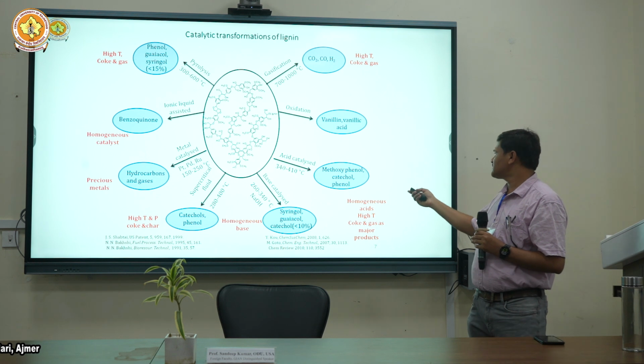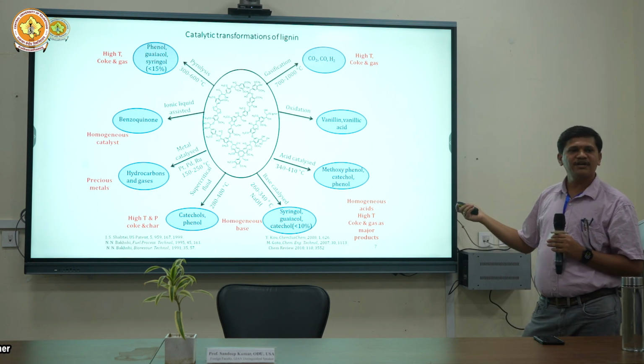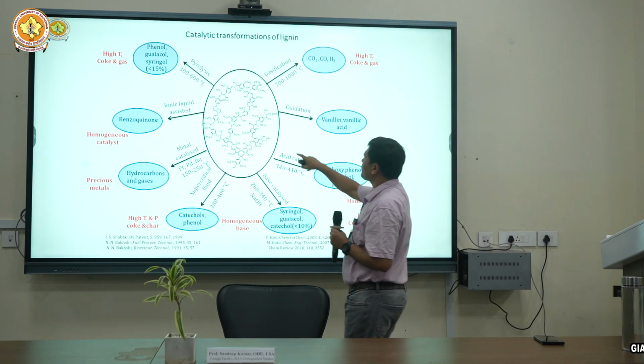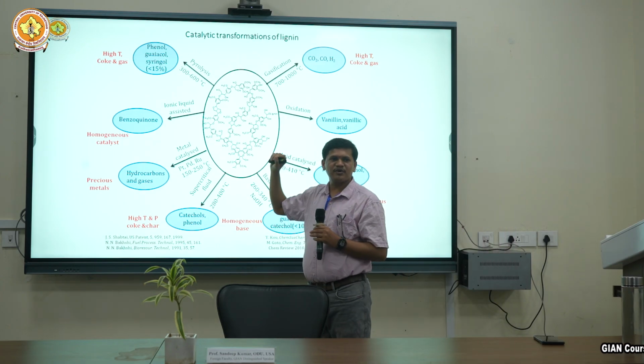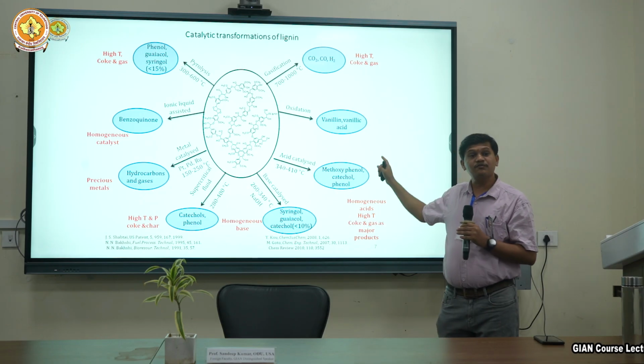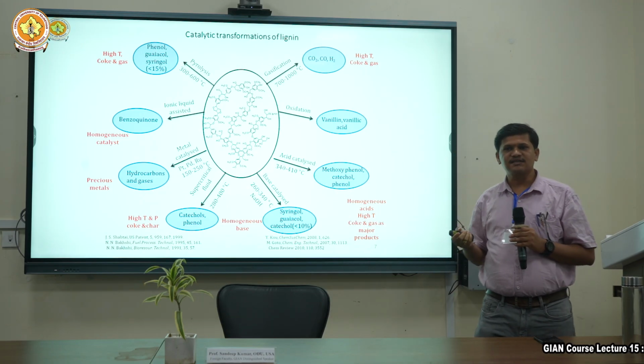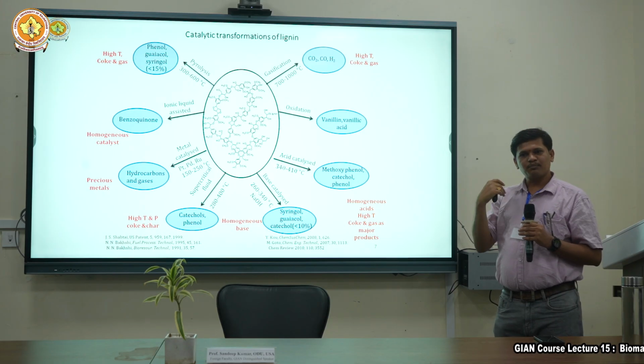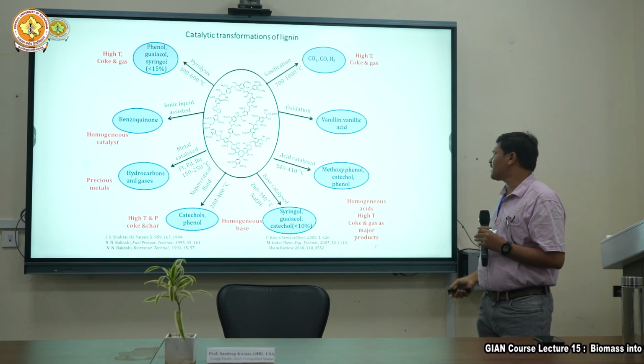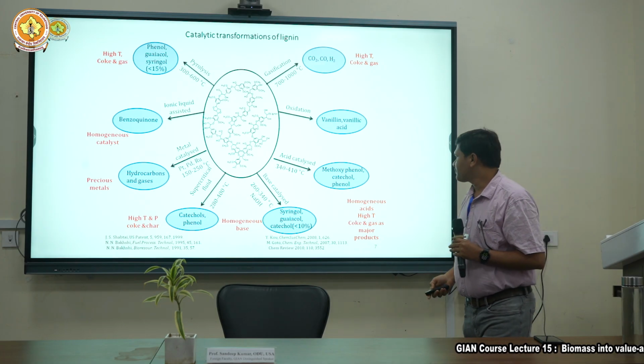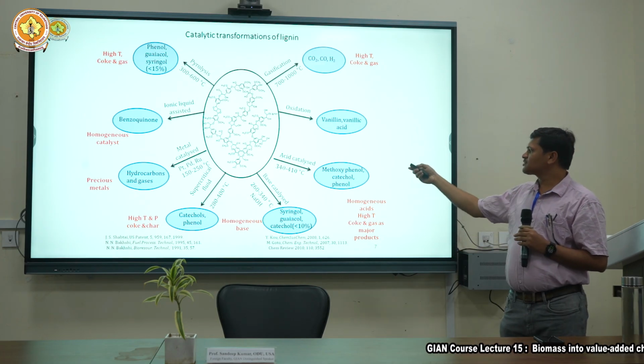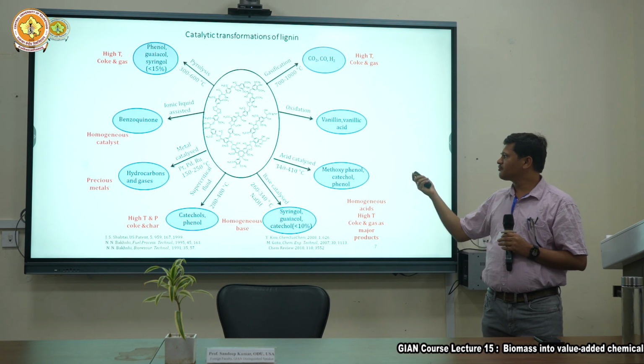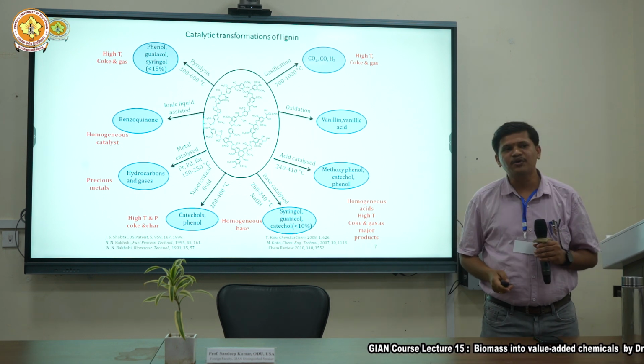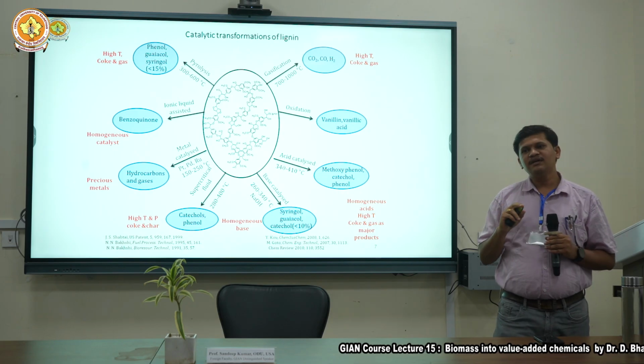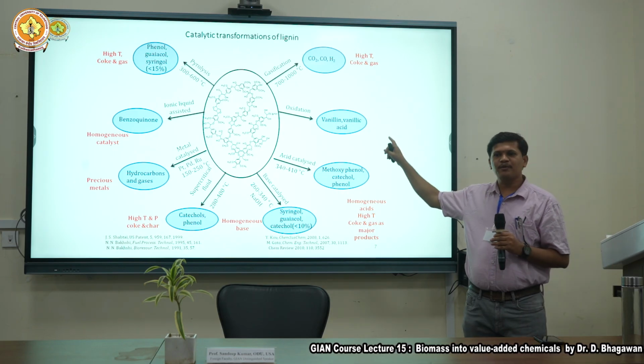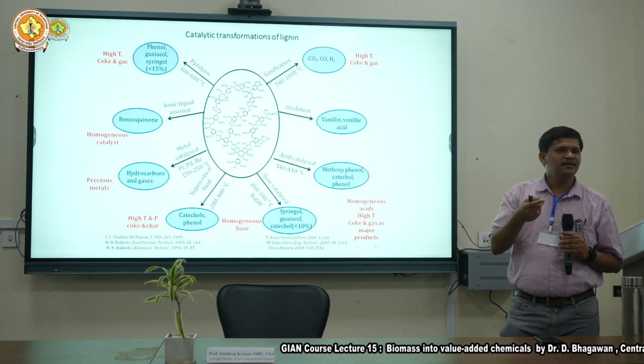And next one is acid catalysis, giving methoxyphenol, catechol, phenol components. So we are just breaking this polymer into smaller components, monomers. That way we are getting all these compounds which we are importing or depending on other nations for. That dependency will reduce and our production rate will increase by converting all these things. And base catalysis gives cresol and catechol. And if we go for supercritical fluid, then phenolic components. And if we go for metal catalyst, then hydrocarbon and gaseous components are possible to generate from the lignin. So these are the different mechanisms and their byproducts which are possible to get from the lignin waste.